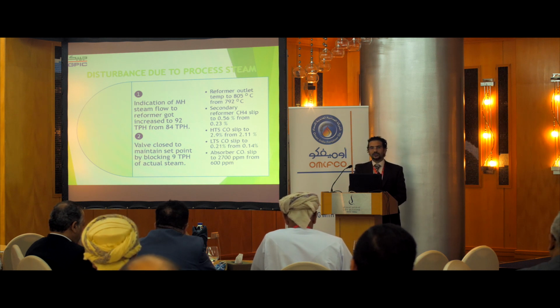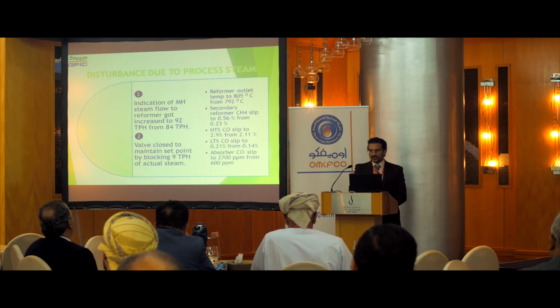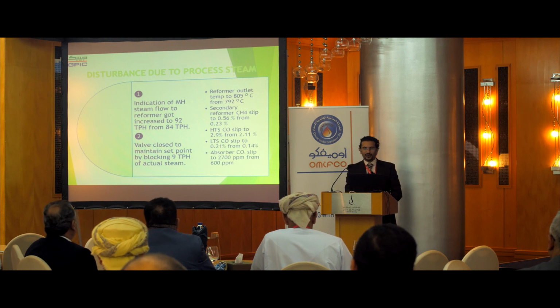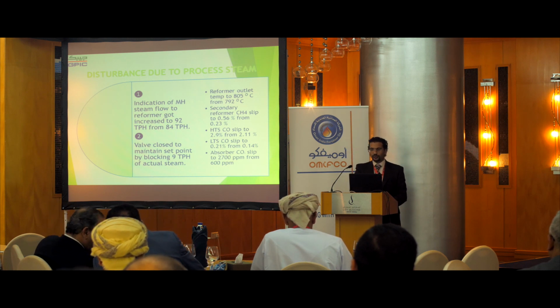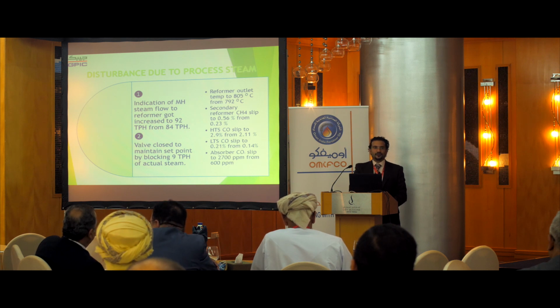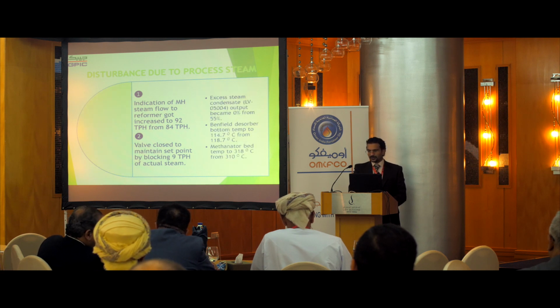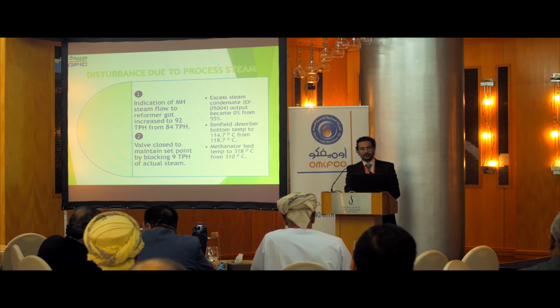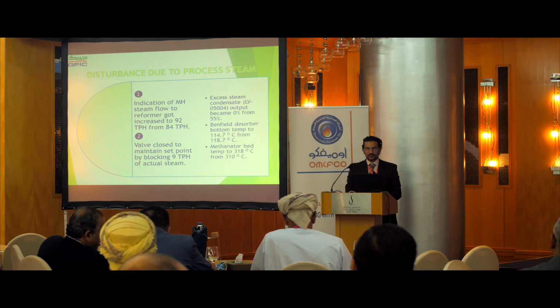Reformer outlet temperature went up to 805. Our CH4 slip from the second reformer went to 0.56; it's regularly 0.23. HTS CO slip went to 2.9. LTS CO slip went to 0.21. CO2 slip also jumped to 2,700 ppm. And this also increased our methanator temperature, which almost caused a trip.